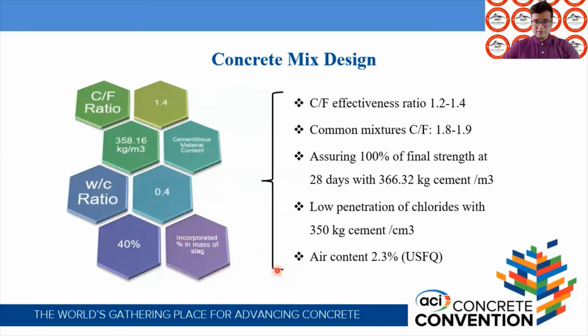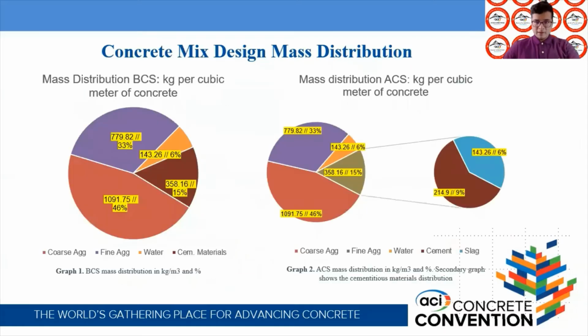The final concrete mix design is presented here. The same amount in kilograms of cementitious materials, water, and aggregate per cubic meter was used, as shown in graphs 1 and 2. For the alternate case mix design, 40% of the overall cementitious materials were replaced with slag, corresponding to 6% in mass of the overall mix design.